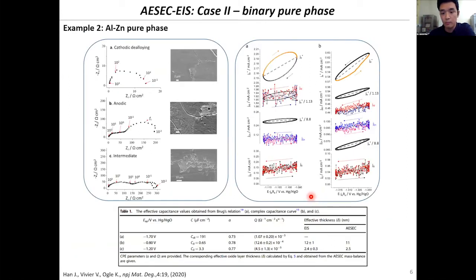So by this coupling with this binary phase, we can still do conventional electrochemical impedance spectroscopy, such as the Nyquist plot, and we can also obtain the capacitance or CPE, constant phase element, parameters with conventional impedance. We can also estimate the thickness, which shows a good correlation between the estimation from impedance and the AESEC mass balance technique in different potential domains. And we can construct, as you can see on the right side, the elementally resolved Lissajous plots, which will allow us to estimate the dissolution kinetics of each element.